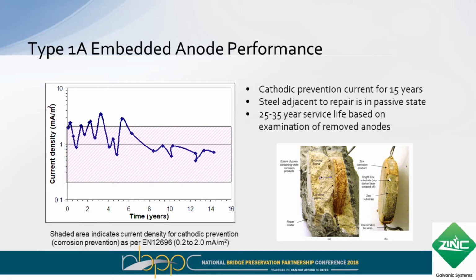And these were measured to be within the band for cathodic prevention as defined by the European standard, which is 0.2 to 2 milliamps per square meter. And so by taking these out and physically measuring the service life, it's estimated 25, 35 years based upon this certain installation. That's probably a little bit higher than a lot of other places, to be honest with you, but that was based upon some forensics.